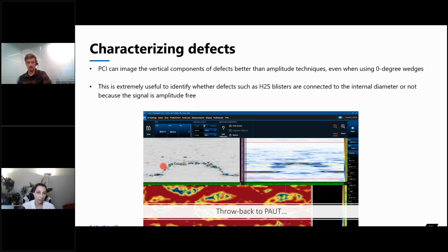If it's not connected here and it's just a blister, the component can remain in service for quite a long time. But if not, again, it can create quite important damage, and it can burst very quickly. So that's what I wanted to show here. I put a little throwback to PAUT, and that's what we're seeing here. This is still an advanced technique, right? We're still looking at phased array. It's used heavily. It is still a very valid technique, obviously, but look at the difference for that blister. We can see very loudly the amplitude here, and for what's parallel to the surface we have a very nice reflector, so we know there's a blister, but do we know for a fact that it is connected here? I would probably want to use another method or another angle, another scan basically, to know what's going on there and to make sure that it's not connected to the ID.